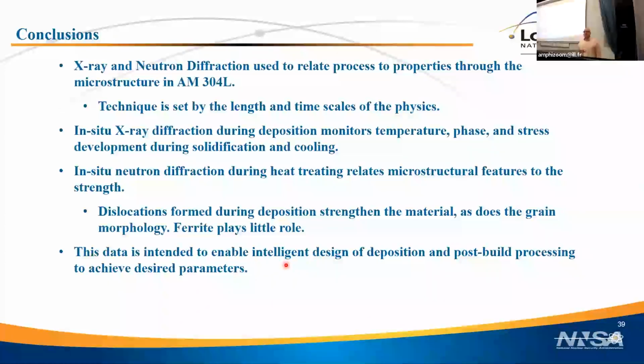We are very much in this discussion of the convoluting, the different. And I have a question regarding the chemical segregation, because we are also trying to figure that out with respect to the build height, because we observe not only these different phase partitioning and metastable phases, but also for the same phase, different chemistry along the build height. So I don't know if you have a. Are you talking about titanium? I would guess. One of them.